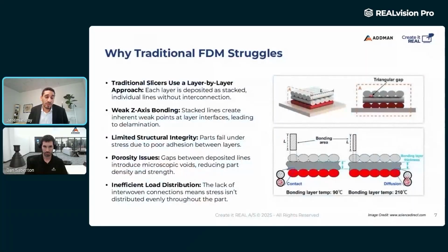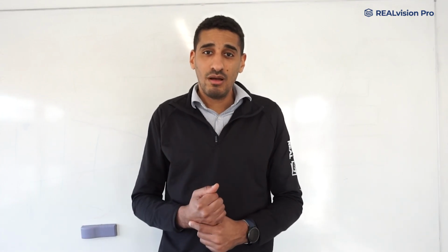Let's look at why. In FDM, you're creating parts layer by layer, making beads that you deposit. Even though the parts are extremely close to injection molding in the XY direction, you end up with very weak Z-axis bonding. It means you have limited structural integrity, and parts usually fail through the layers. If you stress an FDM printed part, you will usually break it through the layer. There's also a porosity issue because the beads, when you print, are not perfect. They're not square. They are more like round, and that leaves gaps between the beads. In the end, you have a part that is not isotropic, with an inefficient load distribution.